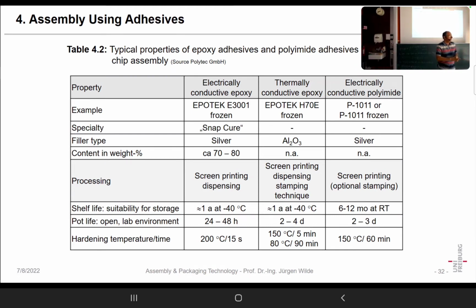That is for normal epoxies, but that here is a special snap cure epoxy. It reacts a little different. You could say below a certain temperature, mostly nothing happens, but above a certain temperature, it suddenly starts to react. And the reason is such snap cure materials often have a hardener that is micro encapsulated. That's a trick in polymer chemistry.